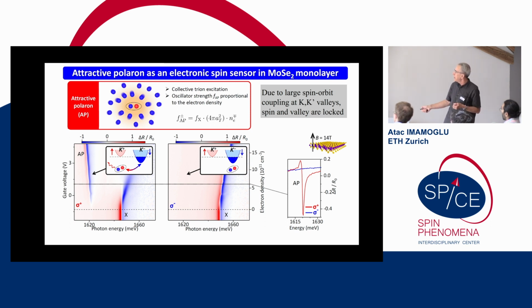You see that the attractive polaron is loud and strong in sigma plus, and it's completely absent in sigma minus. This is the line cut which shows this feature. In this case, we have polarized all of our electrons in the K prime or minus K valley, which means that we can form attractive polarons in K plus and none in the other.